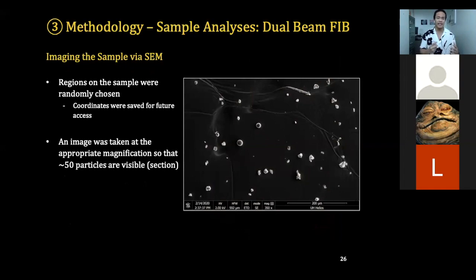An image was then taken at the appropriate magnification so that approximately 50 or so particles are visible on the screen, which we then call a section. The reason for the number 50 was so that we can analyze a lot of particles within one section, but not too much so that it gets too overwhelming when we're trying to label each individual particle.